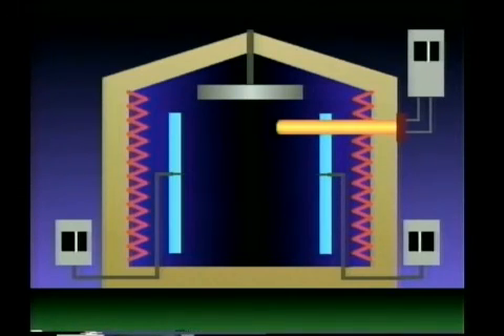A minimum of 9 panels are surveyed on each side, facing a wall which has heating elements in the side wall of the furnace. The survey is conducted by loading the rack into the furnace and measuring the temperature of the panels as the furnace recovers and progresses through a simulated soak period. The temperature measurement of the panels will show any evidence of radiation heating from the sidewall.